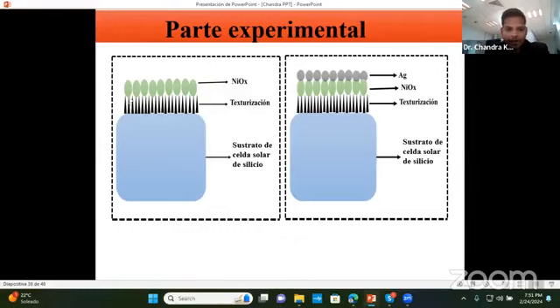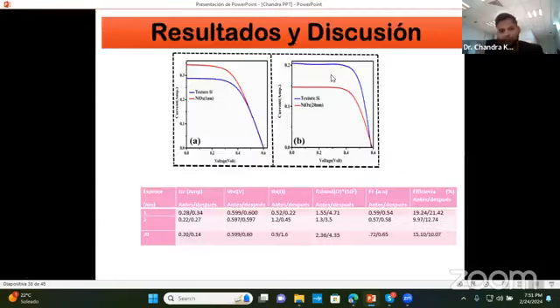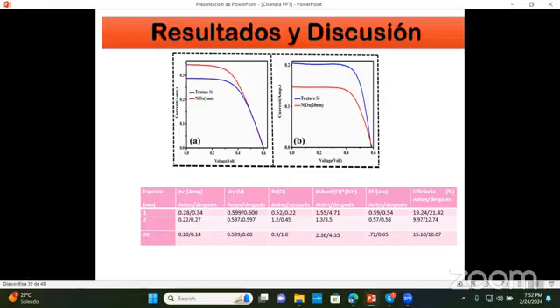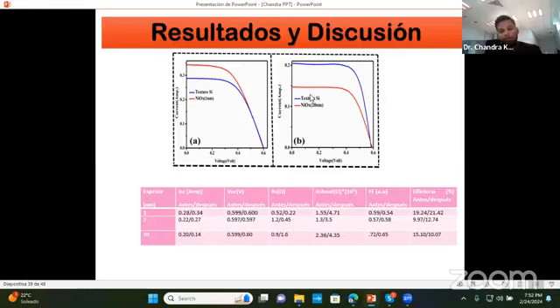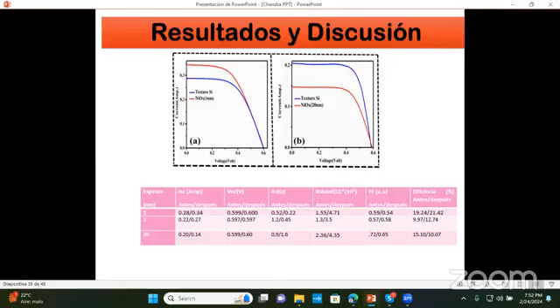a solar cell substrate. After texturization, we have deposited a nickel oxide thin film, NiOx. And in the second part, we have deposited NiOx and silver, and we have studied the different outcomes. If we compare textured silicon, this is here, and we have deposited 1 nanometer, then the short circuit current rapidly increased. But in the case of 20 nanometer, we got some negative outcome because of the thicker layer.